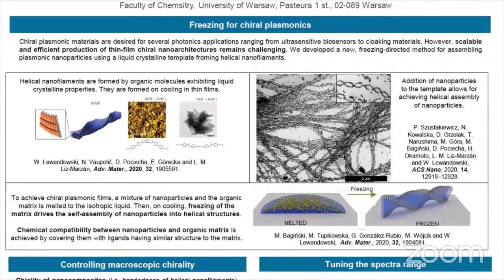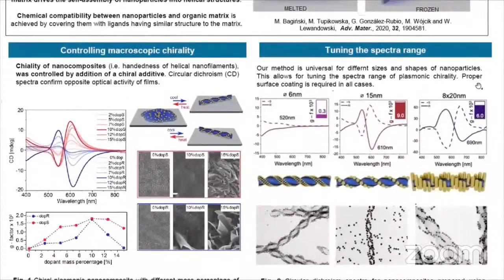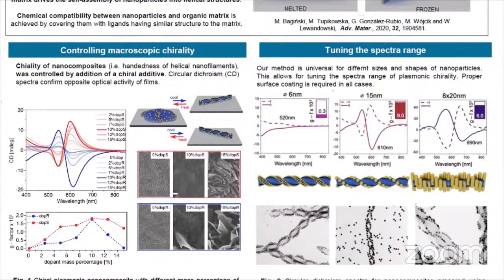In one of our recent papers, we have shown how to use this strategy to produce chiral plasmonic films that exhibit chiral response on the microscale. So small domains of one handedness were produced, and we confirmed that they interact with circularly polarized light in a different way. However, in our recent work, we aimed to develop the ability to produce macroscopic bulk scale systems which exhibit either right or left-handed properties.